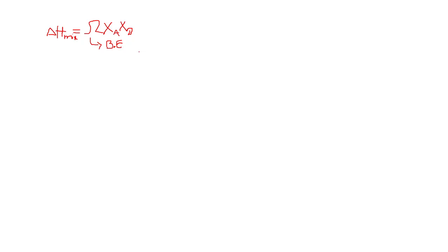So if our final product is AB and it is more negative, then it is the bond energy of AB minus half times the bond energy of AA plus the bond energy of BB. Now if my bond energy of AB is negative, then it will dominate the whole term. So that's why we will finally end up with delta H mix as a negative term. Now what happens if the AA bond energy and BB bond energy are more negative when compared to the AB bond energy? At first we have the AB bond energy as more negative than AA and BB.